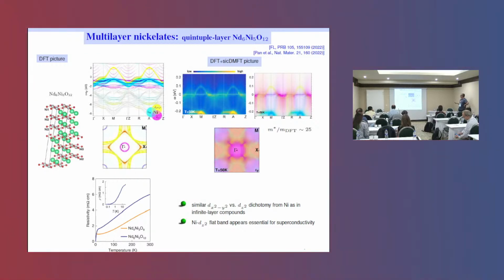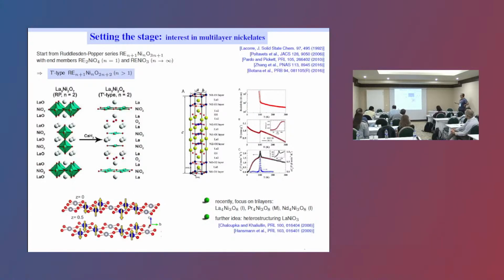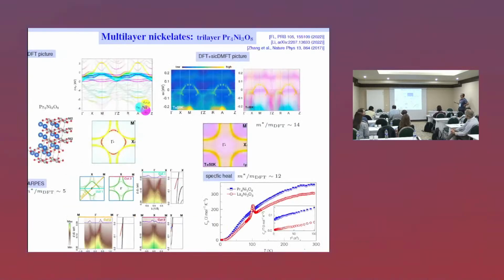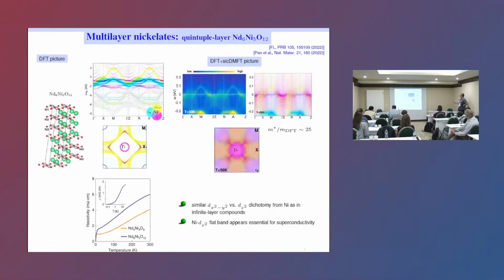And the main message here is that we again see this nickel dz² like flat band. We have some x²−y² dispersions, but they are far from the arc-like structure as we know from cuprates. So again, we have a shifting through of this nickel dz², and that is really translating well to the infinite layer kind, whereas for the 3-layer compound, very quickly just to get the story across: for the 3-layer compound, this flat band is above because we're already much more in the overdoped region, whereas for the 5-layer, it's right at the Fermi level, and this triggers then also the superconducting instability. But the coherence scale is much lower.